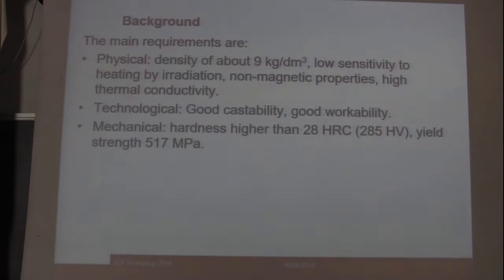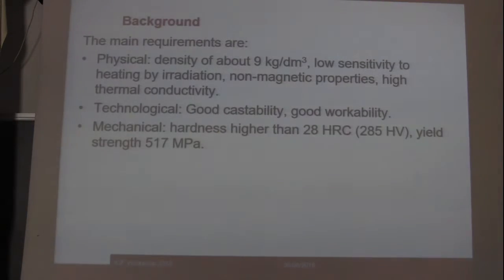We need to keep in mind that we need to produce a sphere, so we also have technological requirements such as good castability, because we need to produce a sphere having a diameter of about 40 centimeters, and good workability, because we need to produce cavities on the surface of this sphere. We have also mechanical requirements, so we need a hardness higher than 28 Rockwell C and a yield strength of about 500 megapascal.